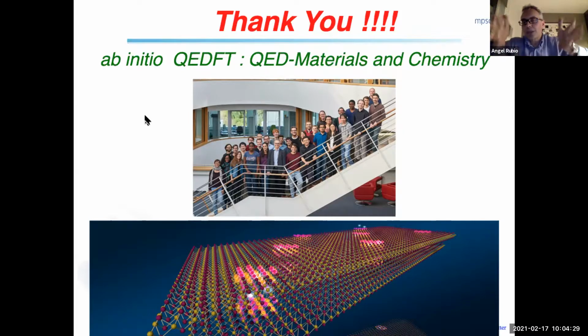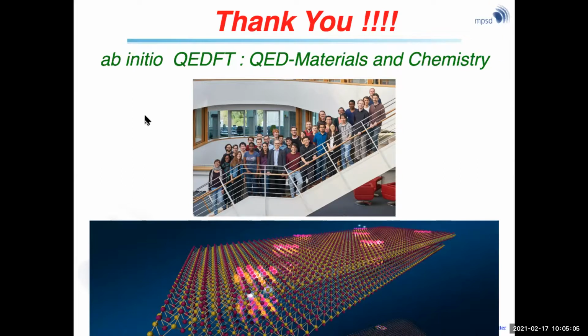In reality, when you put the STO in the cavity, the interaction between the STO and the matrix and the STO and the mirrors might introduce a little bit of strain. And that will be another non-linearity that opens the door to induce the ferroelectric transition. But assuming this effect is minor or negligible, because you isolate the STO as much as you can, then the effect of having the para to ferroelectric is possible because the potential energy surface that I showed you is really non-parabolic, is beyond the harmonic. And the non-linearity is important.